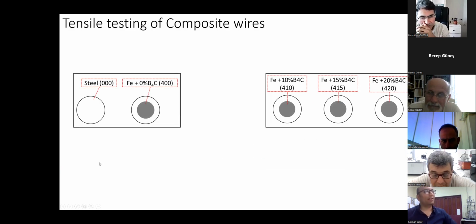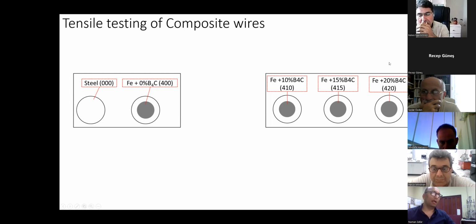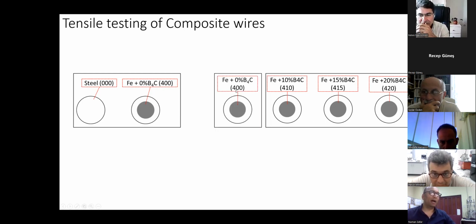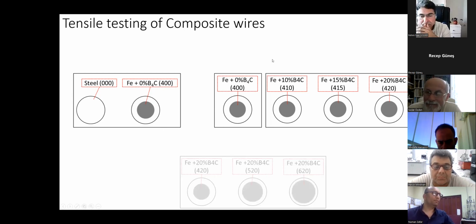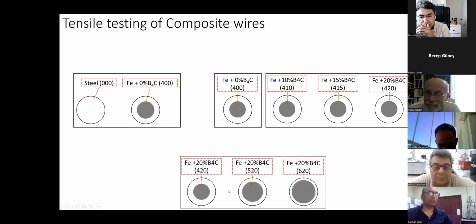So tensile testing of the wires is reported. I have compared the 000 specimen with the 400 specimen. I have checked the influence of increasing reinforcement ratios on the material. And I have compared this increasing reinforcement ratio of the B4C particles with an unreinforced 400 specimen because it does not have any B4C particles. All of these experiments are repeated for the pre-sinter and the post-sinter state. And here I have studied the influence of increasing core size, again for the pre-sinter state and the post-sinter state.